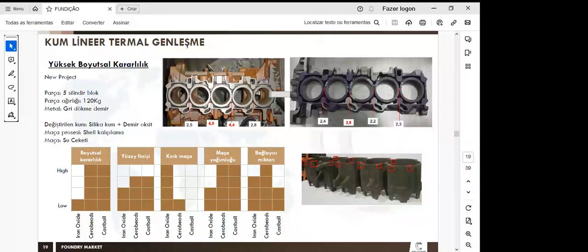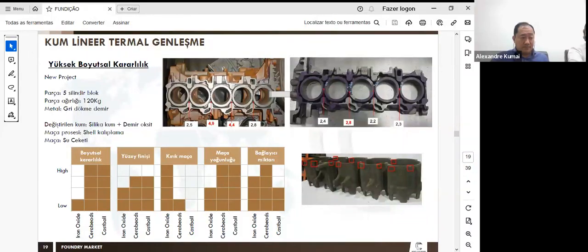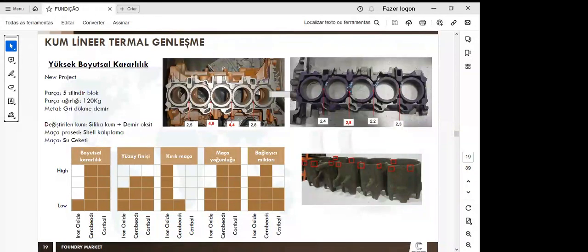However, Castball presents better results than ceramics regarding binder content reduction and broken core scrap. We can see in these graphics below, broken cores with Castball, this problem we're solving. And about the binder, in the last graphic, we can reduce the binder content when we replace Mullite sand with Castball. We can reduce the binder content a lot in the shell process in this case.